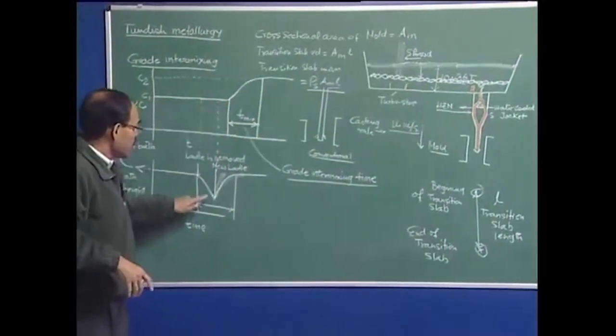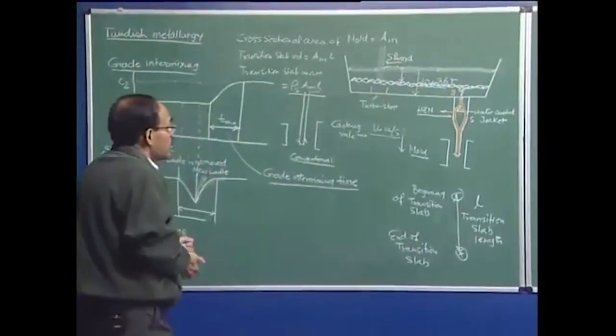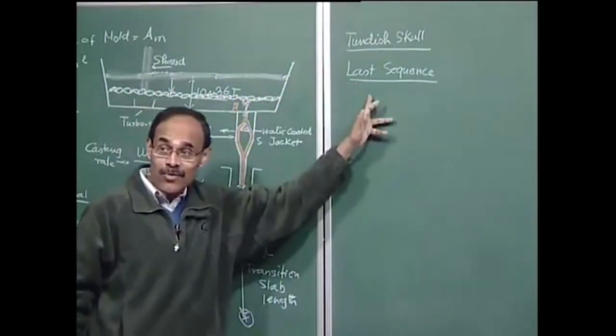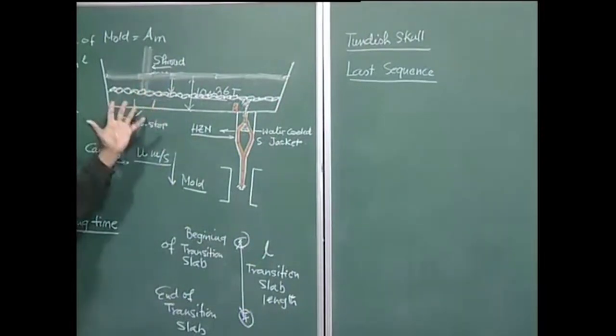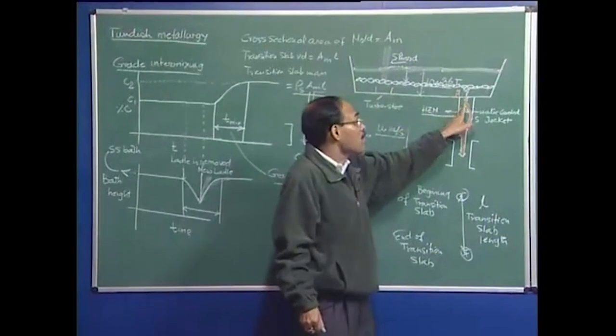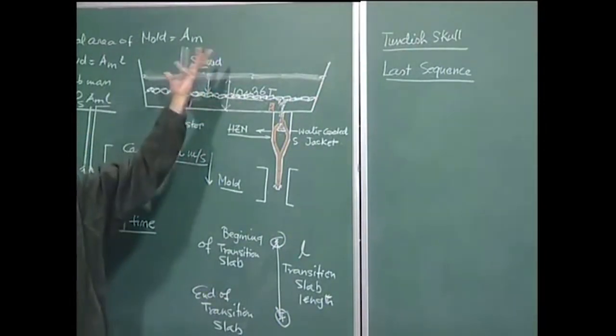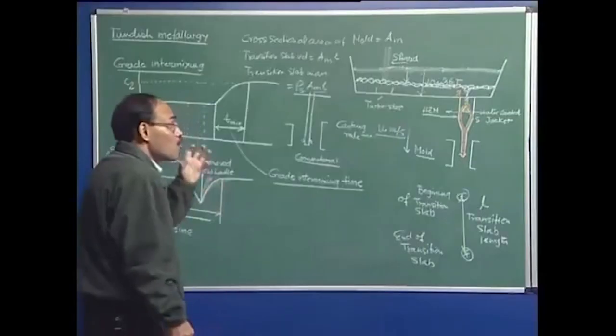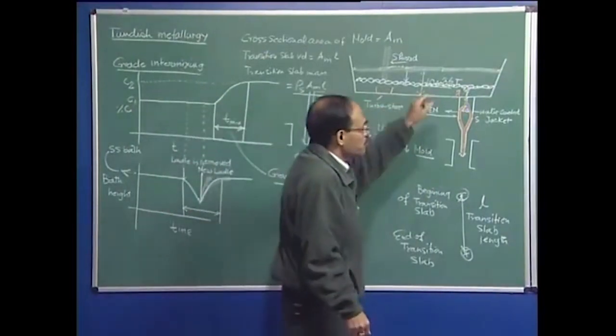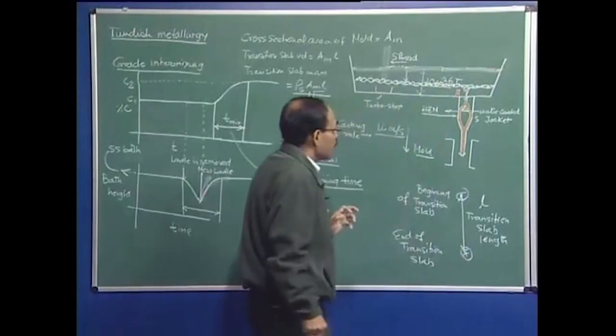Opening the second ladle when the bath is at a comfortable level gives rise to a longer transition slab volume. So the liquid level and transition slab volume have to be optimized simultaneously — we do not want slag entrainment, but we also do not want a larger transition slab volume. The rate at which molten metal is fed into the Tundish and the level of residual liquid have to be really optimized to take care of both Tundish skull and intermix slab volume.